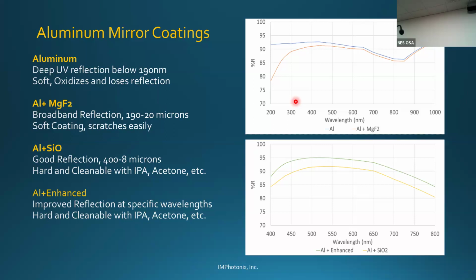That's really the only good metal to use if you're looking for cheap UV reflectance mirrors. But aluminum also has benefits in the visible and in the near IR, as long as we can protect it to make it hard, usually with a quartz or SiO2 overcoat. And then with other dielectric films of high index and low index, we can enhance the reflectance to practically 95, 96%.